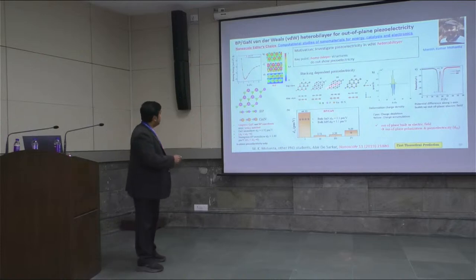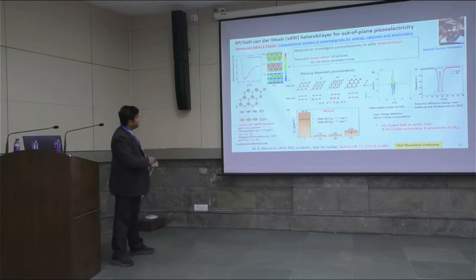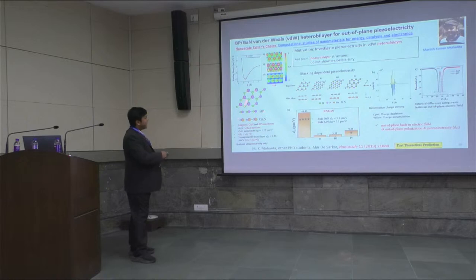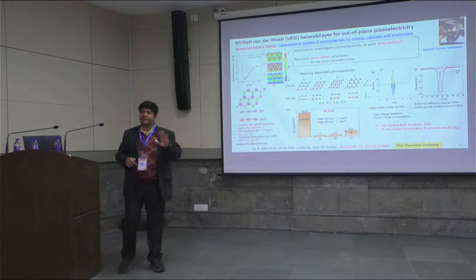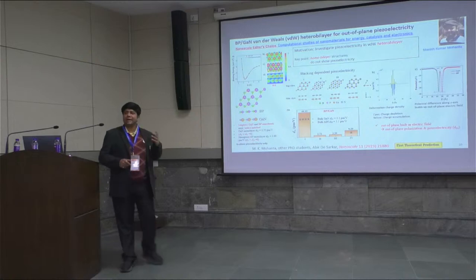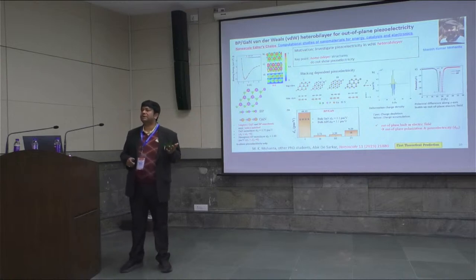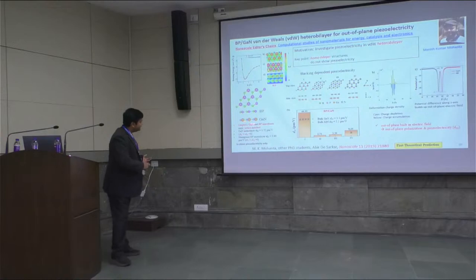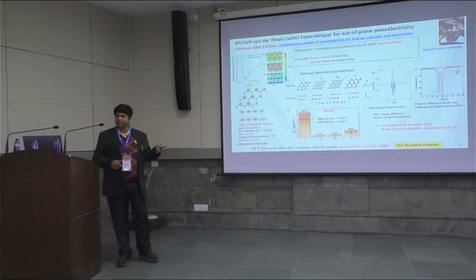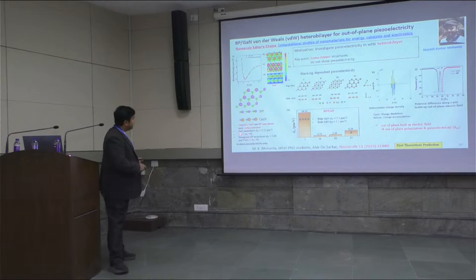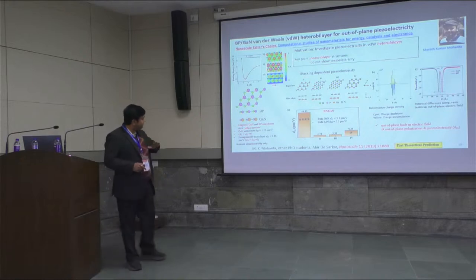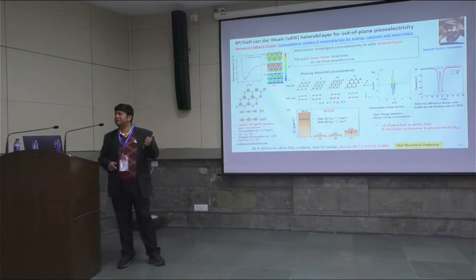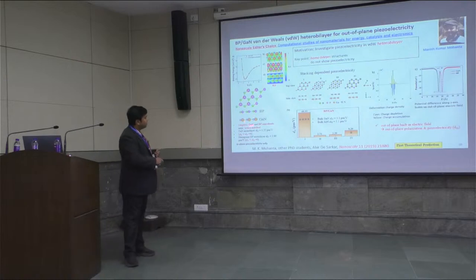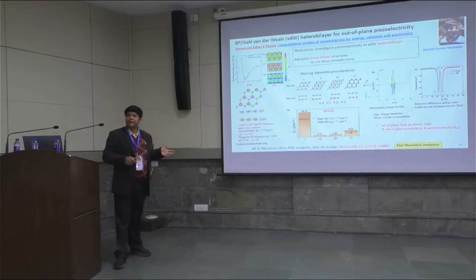So what Manish did is that he designed this van der Waals hetero bilayer consisting of a single layer of boron phosphide stacked on top of a gallium nitride monolayer. These monolayers are very close in lattice constant, and therefore computationally it is not demanding to handle such calculations. And experimentally also these nanosheets exist, so these are of experimental relevance. Now these individual monolayers only show in-plane piezoelectricity. They do not show any out-of-plane piezoelectricity until one is stacked on top of the other to form a van der Waals heterostructure, and then out-of-plane piezoelectricity arises, which is sensitive to the stacking order.